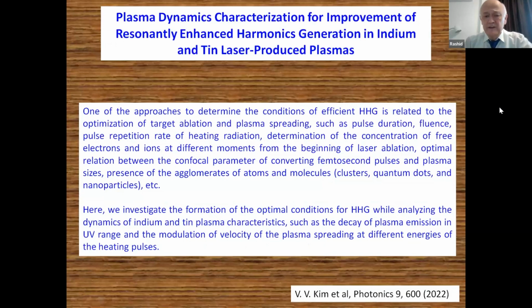Other materials are indium and tin laser-induced plasmas. Those two plasmas were analyzed early, and it was observed that they can provide very strong high-order harmonic generation, especially some single harmonics which are much stronger than neighboring harmonics. To determine the best conditions for those processes, we also analyzed the properties of plasma in our laboratories and created conditions where such materials allow us to generate very strong resonance-enhanced single harmonics, which can be useful for analysis of some materials in the XUV range below 100 nanometers.